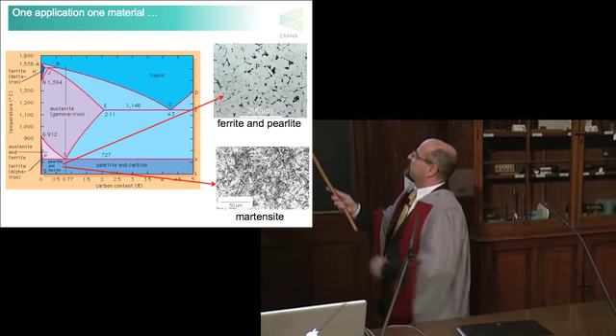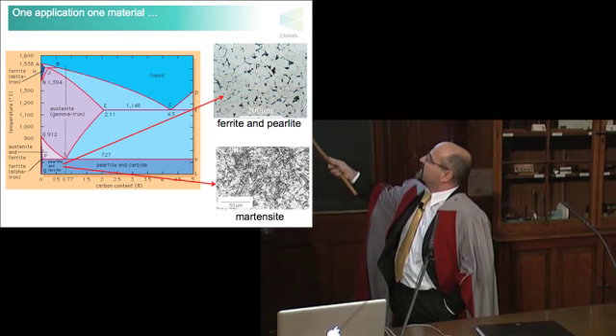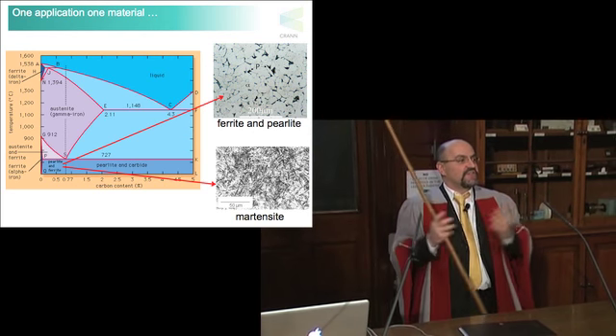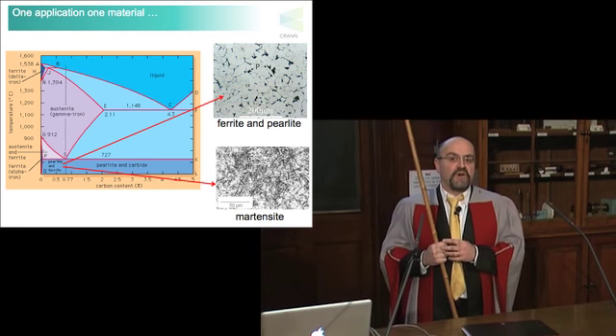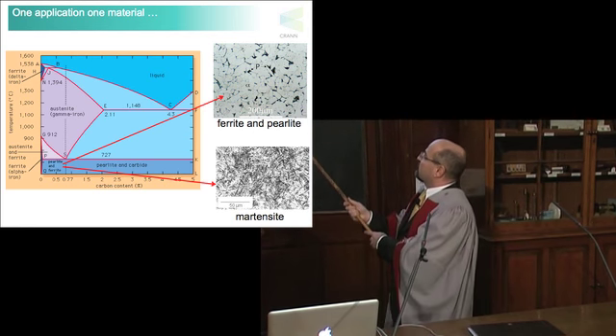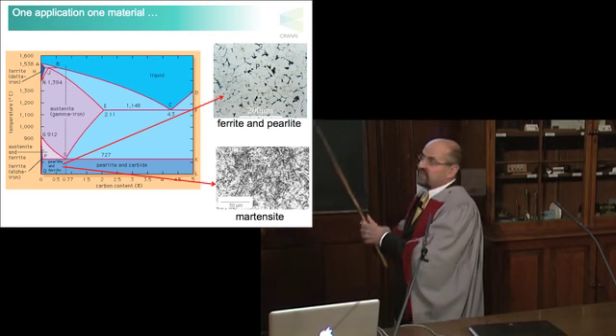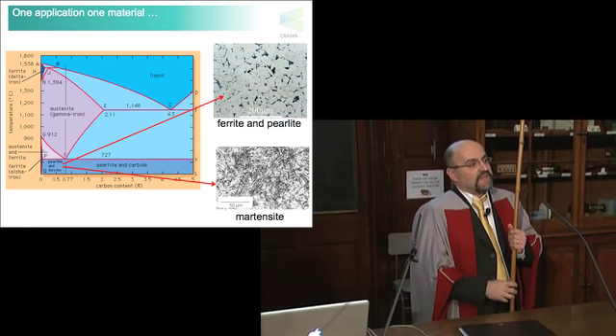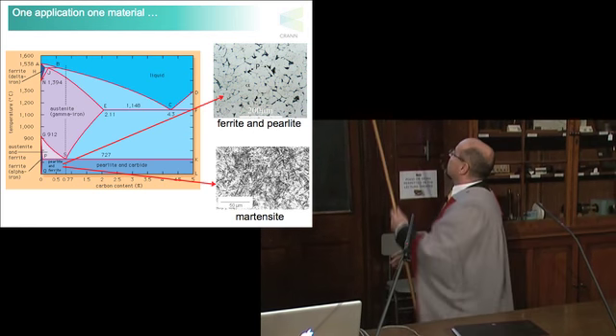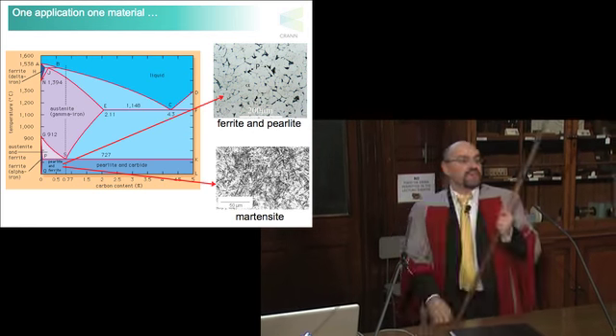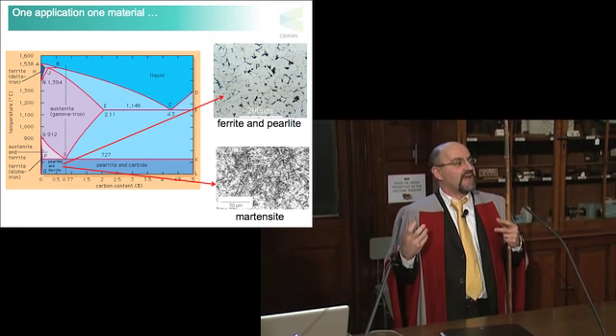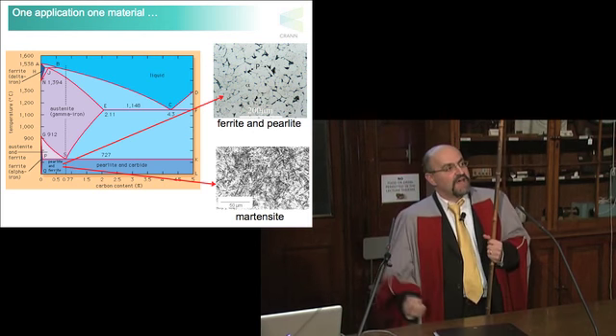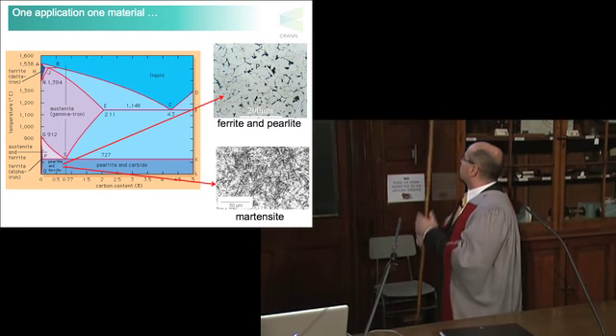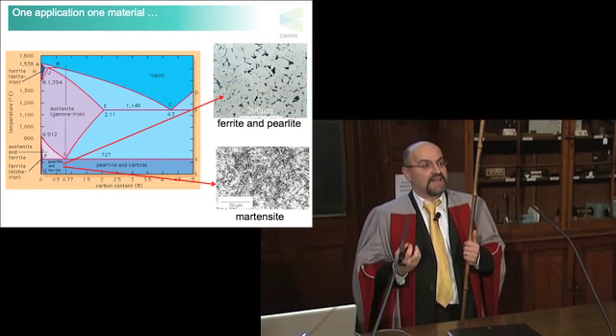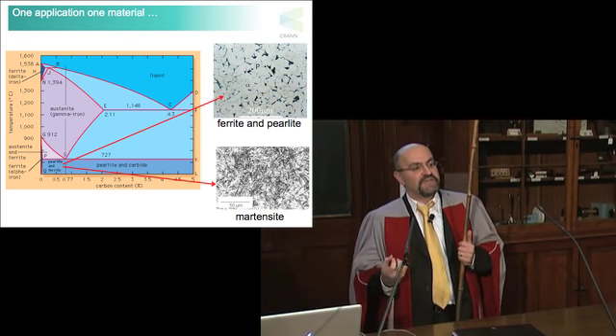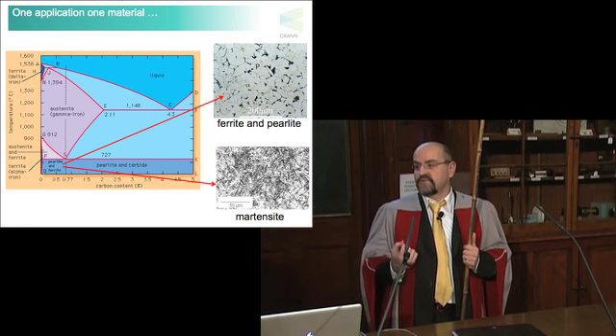The rule of the game is the following. If you heat up steel to about 1,000 degrees, you can dissolve a significant fraction of carbon in iron, up to about 0.7%. Then, if you cool it down slowly, you end up in this type of steel, in which you have grains of different materials with different carbon content, and this is soft. If you cool it down very quickly, you end up in this one, which is called the martensite phase, and this is very hard. So the same material cooling down slowly gives soft steel, and cooling down fast gives hard steel.